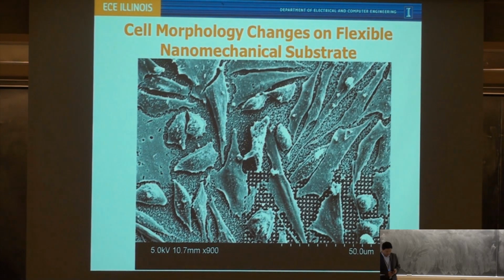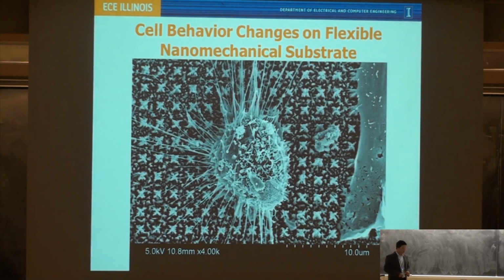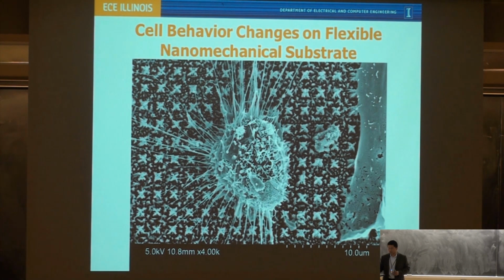So this is more a picture showing that we do have a lot of cells that like to stretch themselves into either a very long shape or a very spread-out thin sheet. That means something's going on. There's something underneath providing a mechanical cue for the cell to spread itself. There must be something that the cell can hang on to stretch itself. That's exactly the case. We observed that many cells grow a lot of filopodia, or tentacles you can say, trying to reach very far away to grab onto those flexible polymer posts and use those posts as the mechanical cue to feed back into the cell growth and migration patterns.